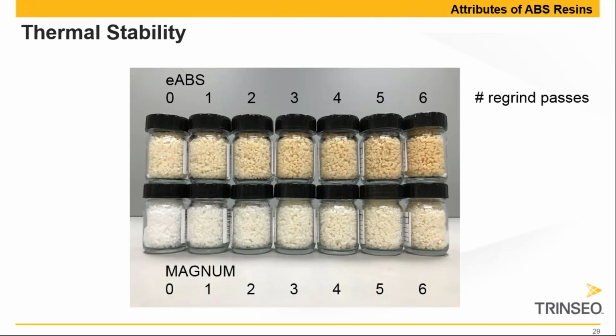In this slide here, we show the difference in thermal stability between Magnum and emulsion ABS. And you see here a series of glass vials numbered from 0 to 6, and they represent different regrind and re-extrusion passes. And 0 is obviously the starting point, and 6 is after 6 regrind passes. You can see that the color change to yellow is much more apparent with emulsion ABS. If you watch carefully for vial 5 and 6, you even see a red shine coming in.